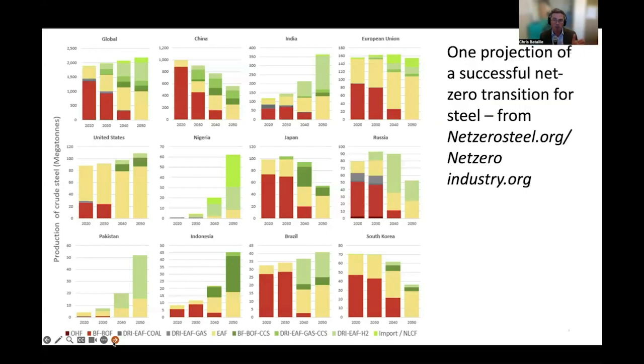If we look at the regional pictures, they all look quite different, however. So if we look at China just to the right, you see demand has come down from just about a gigaton to roughly 600 megatons. The blast furnaces are gone. There's quite a bit more recycling, and there's clean primary iron ore reduction. India is the reverse picture, where demand goes from just over 100 to over 350 megatons. The blast furnaces are gone. There's some recycling, but it's mainly new clean primary or potentially imports of clean steel or clean briquetted iron that allows it to produce the steel that it needs.